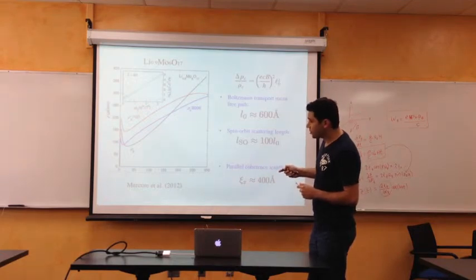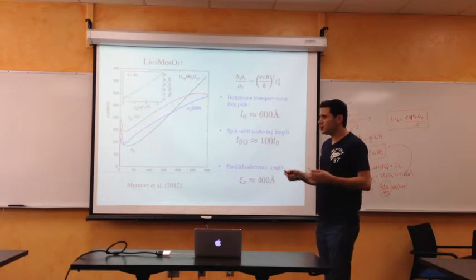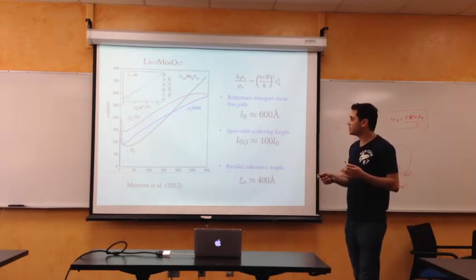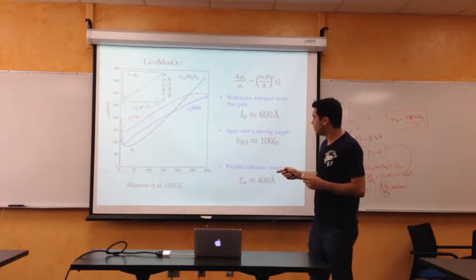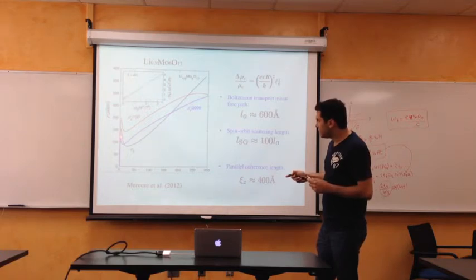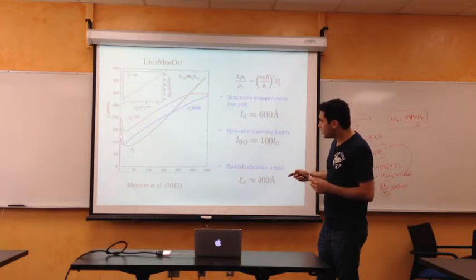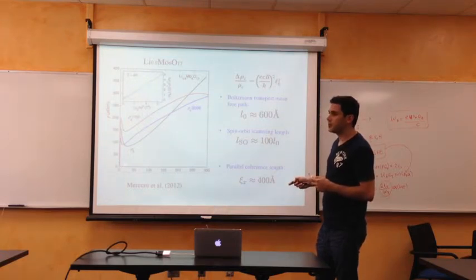Then there is an upturn in resistivity, which generally characterizes a lot of these one-dimensional compounds. So it shows a kind of insulating phase below 15 Kelvin, and then a sharp drop - superconductivity at about 2 Kelvin.